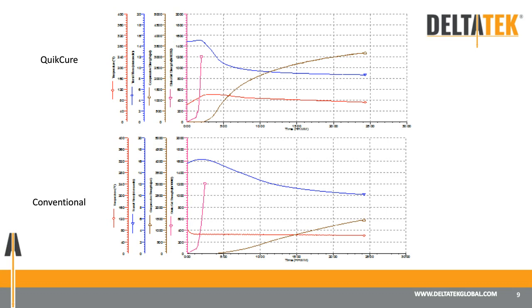And this is down to the capabilities of the lab executing the UCS developments. What we can see on the bottom there, whereby an ambient temperature is attempted to be achieved, is that actually a flat line of the temperature can be seen there around about 65 degrees F, which is pretty warm for ambient temperatures in most parts of the world, especially the North Sea or East Canada.